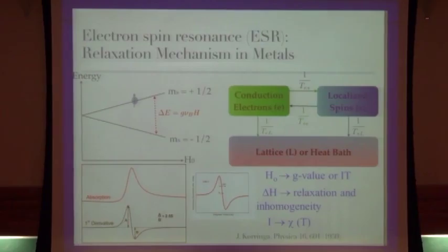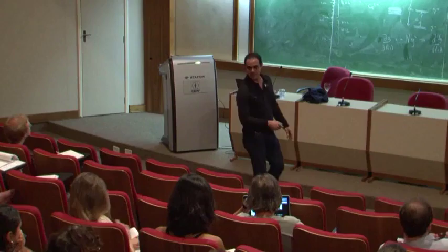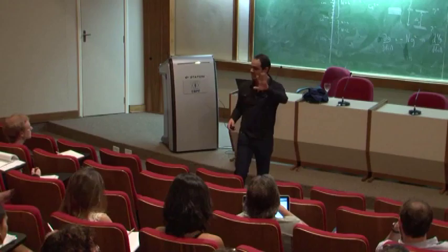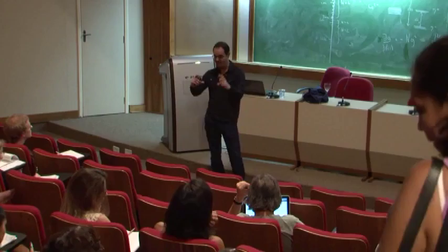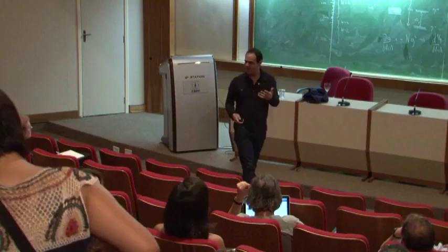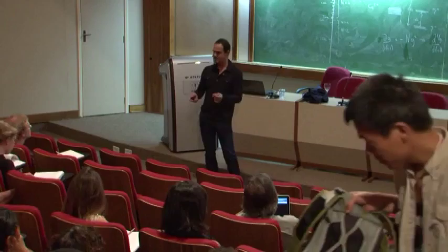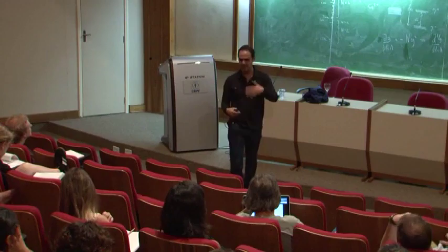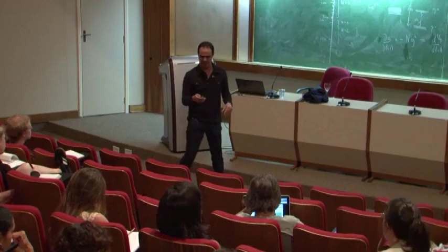Okay, remember the crystal fields? We can also see the crystal fields very well by ESR in two different ways. One can determine the crystal field doublet very well, much better than with neutron experiments. They can measure the energy very well, but we can tell the g value, the wave function of the ground state, to four digits, with very high precision if the line is narrow. So they need to make a model to extract crystal fields, the ones that use neutrons. I don't know if you work with crystal fields, no? Okay, but you can get that directly from inelastic scattering, but we need to do models, fittings to the data, because you measure the energy, and you need to analyze the data to get intensities and get the wave functions. Here we can measure the ground state very precisely, very accurately.